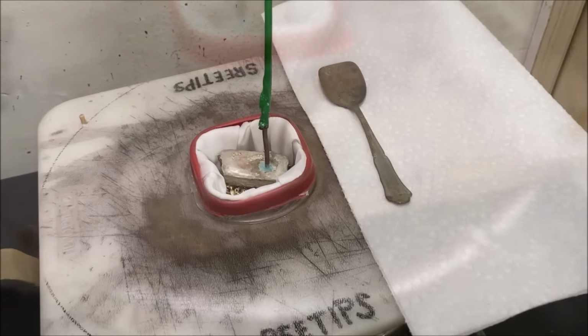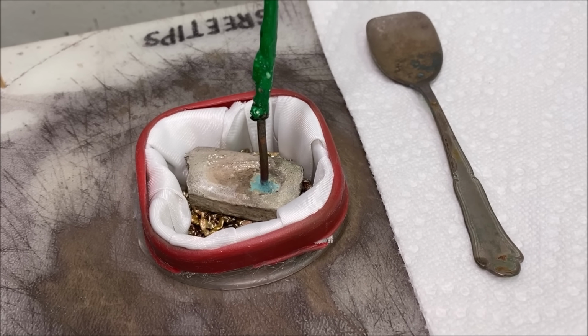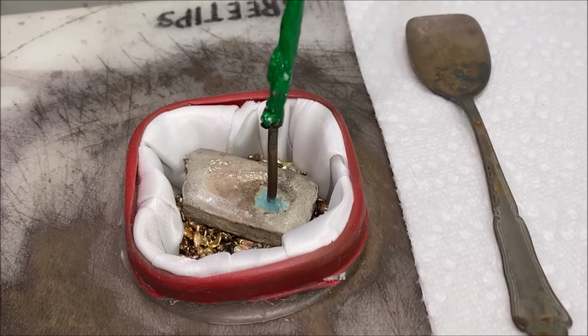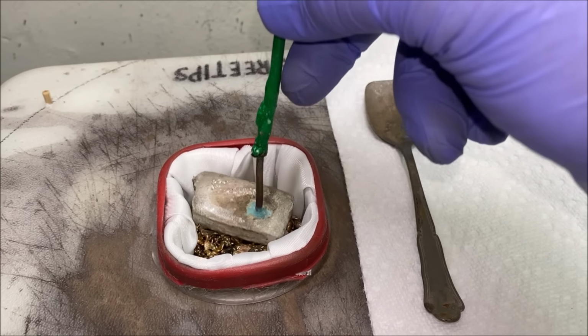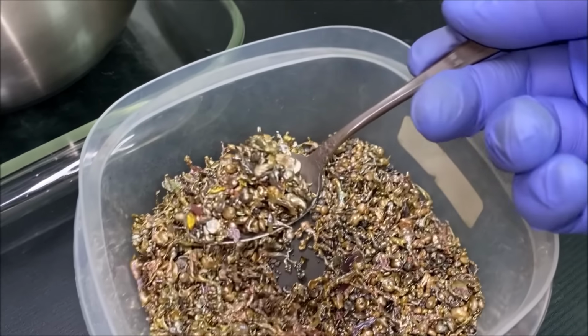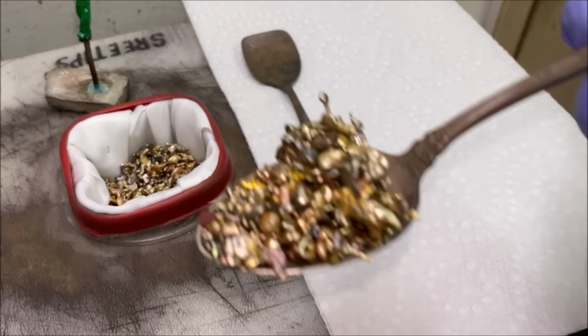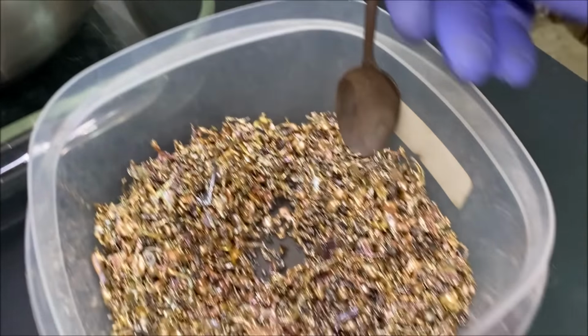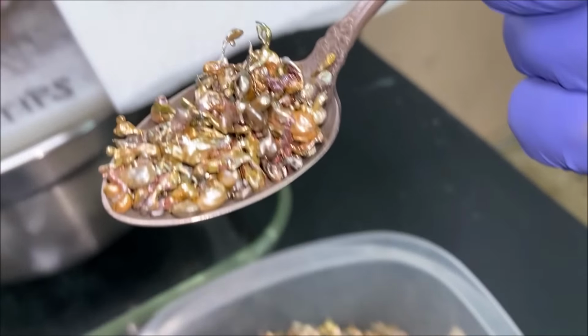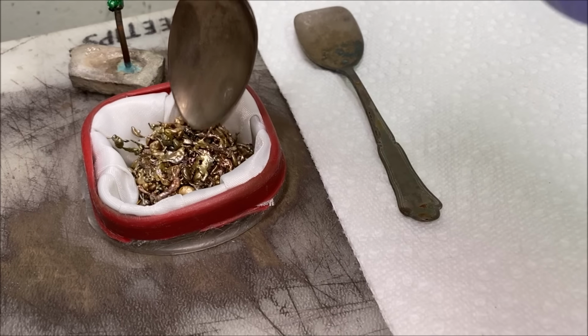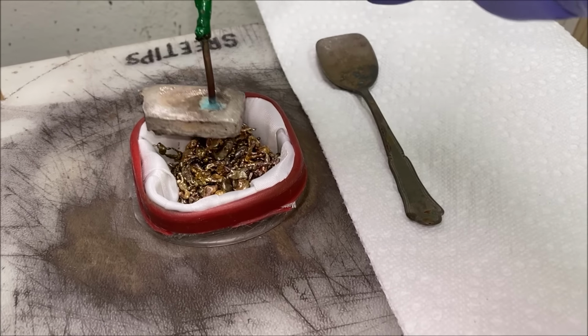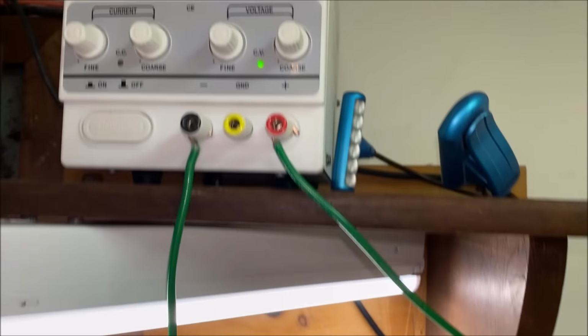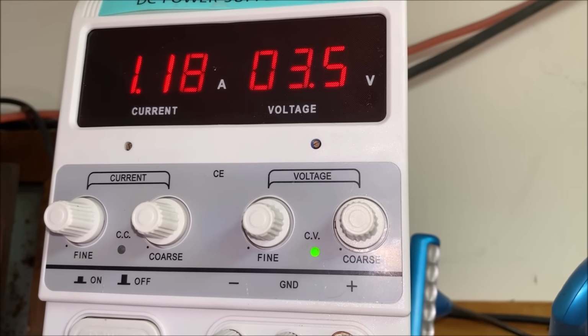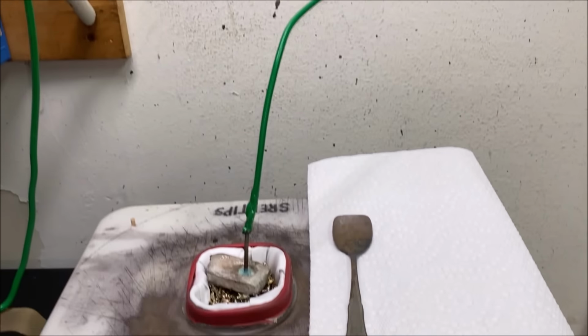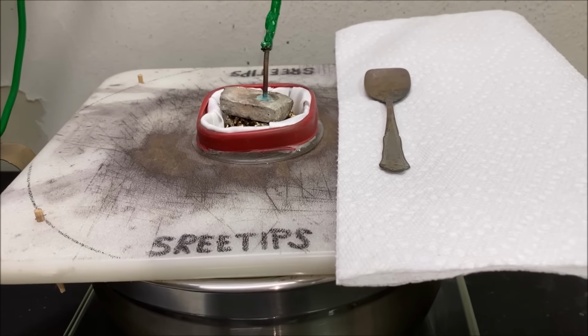What I'll do is, after a day of operation, the silver will dissolve in that anode filter and that level in there will drop. So I just pick it up off of there like this, set it off to the side, come down here and get a little bit more of the impure silver shot granules, and then just add it to the anode filter basket. And then replace the electrode bar. And then we'll just keep doing that for the next 10 days or so. And after about 10 days of operation, we'll end up with about 1.5 kilos of high purity silver.